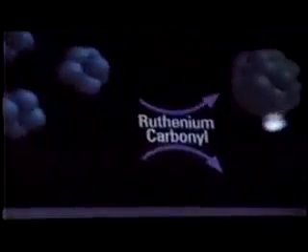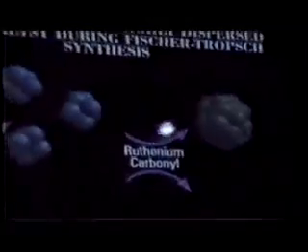During this test, we find ruthenium carbonyl in the cold product receivers. We analyzed the catalyst before and after the test and see a significant drop in the amount of ruthenium in the catalyst. So what's happening here is that highly dispersed ruthenium on alumina forms the volatile ruthenium carbonyl species, and the ruthenium carbonyl gets off from the surface or causes ruthenium migration on the surface.